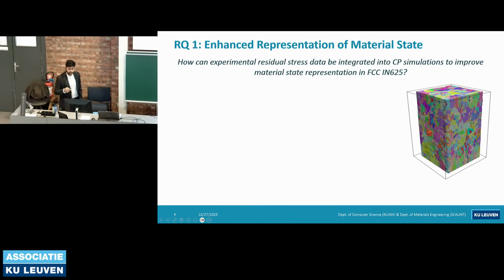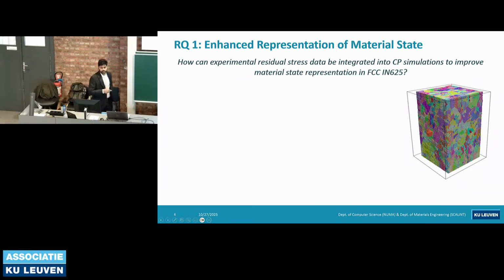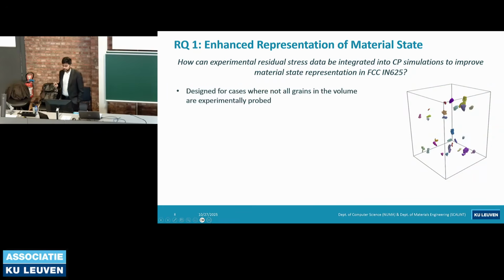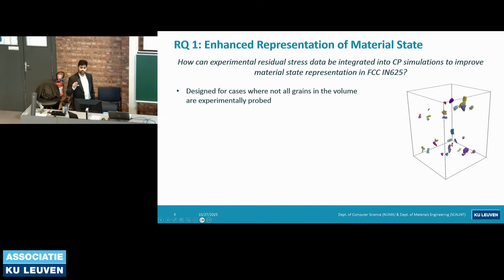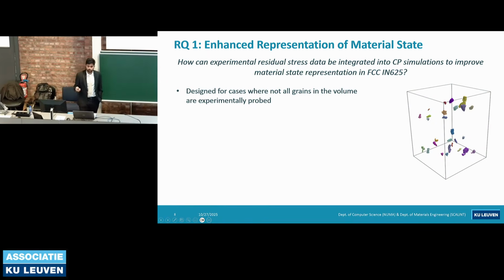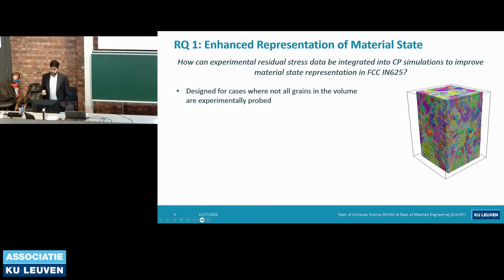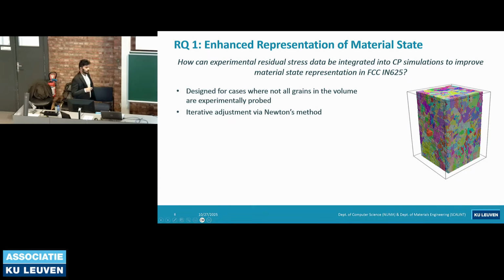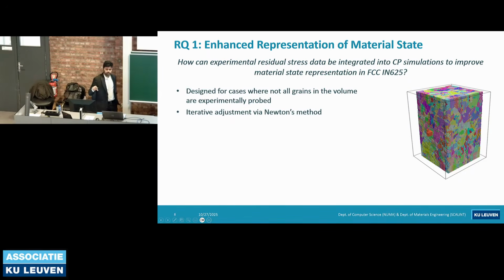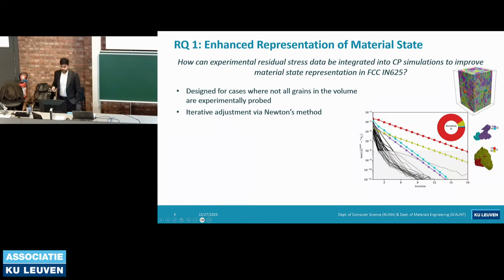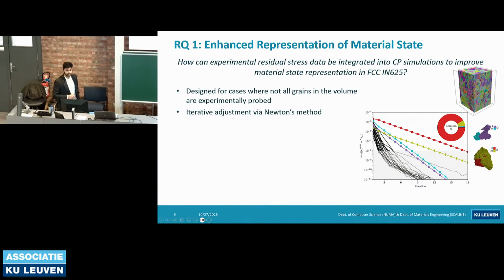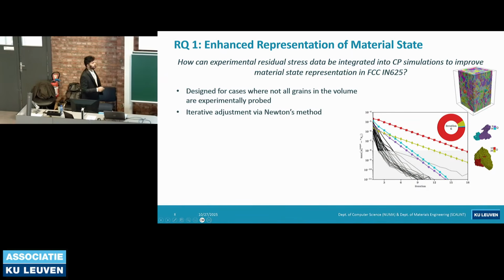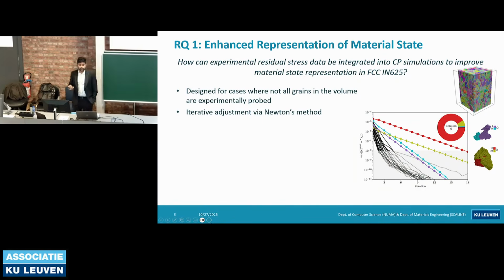A microstructure that was characterized from experiment was used, and this method is designed particularly for the case where you only have residual stress data for a small subset of grains. But this doesn't stop it from being used for the case where the entire volume is characterized for residual stresses. With this, initialization of residual stresses in the volume was made iteratively through Newton's method. As you can see here, the error on the y-axis decreases as the number of iterations increases, which shows that the residual stresses converge to the reference value that we provide.